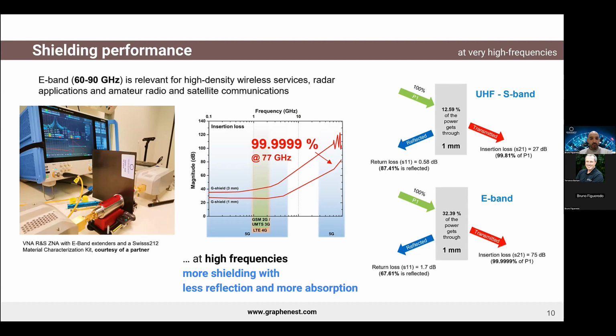Despite the fact that our PVC G-Shield excels at the S-band, it also excels particularly at high frequencies like the E-band. Well, this band, which is 60 to 90 gigahertz, is relevant for high-density wireless services, radar applications, and others. As you can see on the left side of the slide, we have a picture of the equipment that was used by courtesy of a partner.